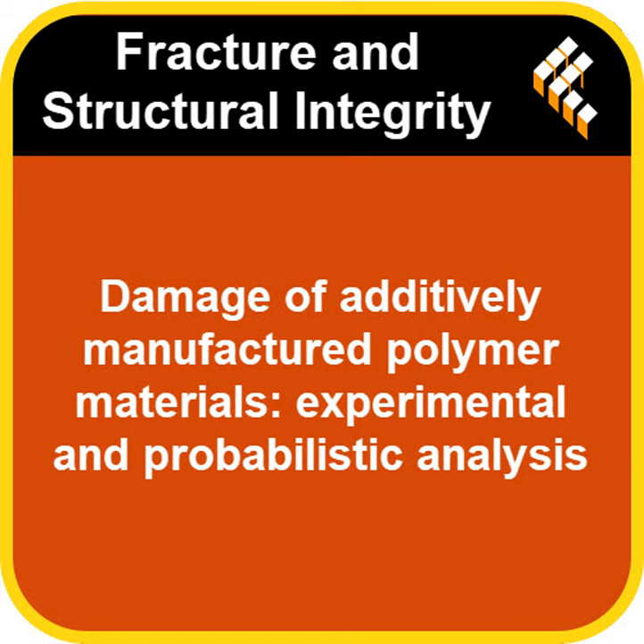And what's really interesting, maybe even a bit surprising, is the study found that while the damage started faster in the initial stages for the weaker 90-degree prints, which kind of makes sense, they're weaker overall, the damage curves for all orientations, 0, 45, and 90 degrees, all sort of converged right around that critical 0.5 life fraction point. Converged, meaning? Meaning they all reached that point where unstable failure was about to kick in at roughly the same relative crack size, that 50% mark. It suggests that once a crack reaches a certain relative size compared to the whole part, the material's likelihood of rapid failure becomes dangerously high, almost regardless of how strong the initial print orientation was. The crack itself dominates. That's a powerful finding.